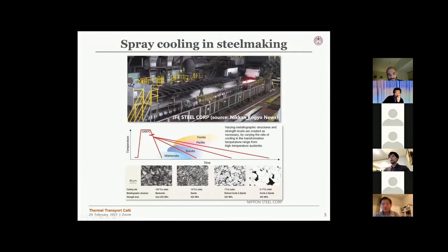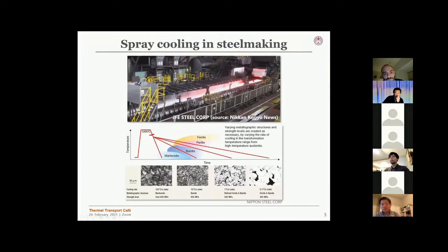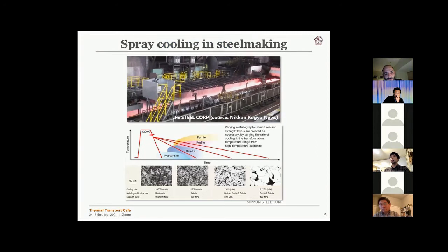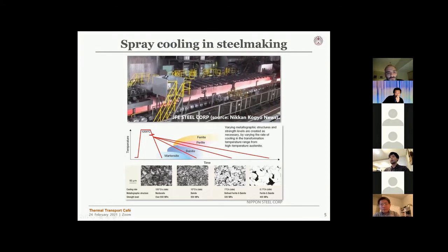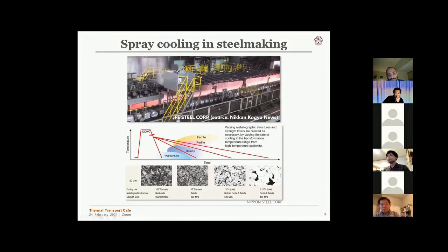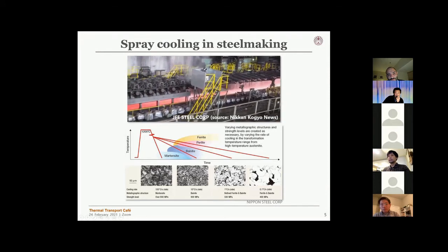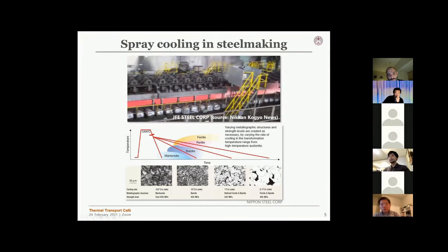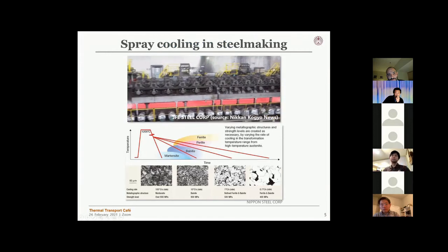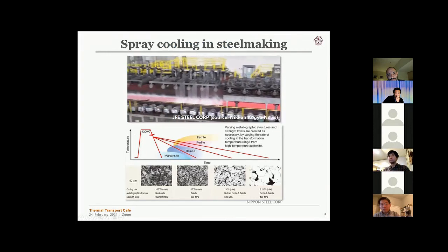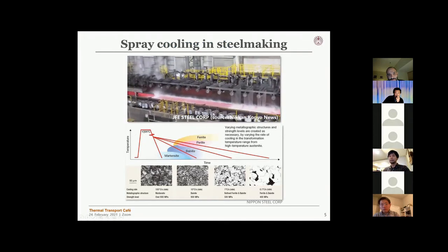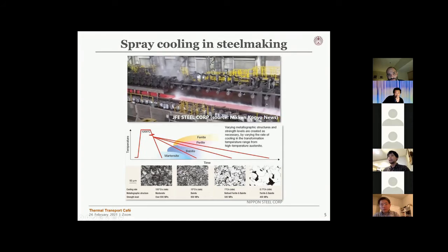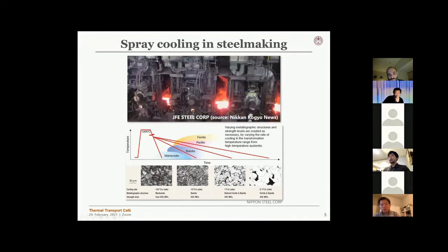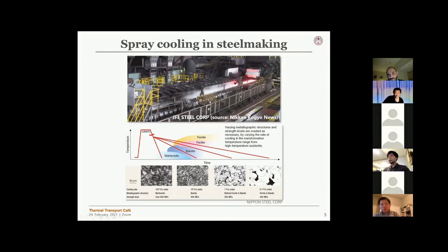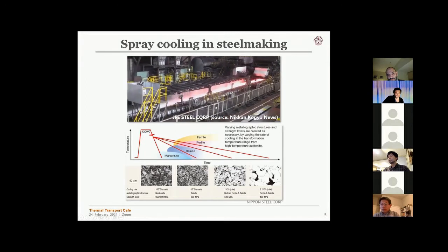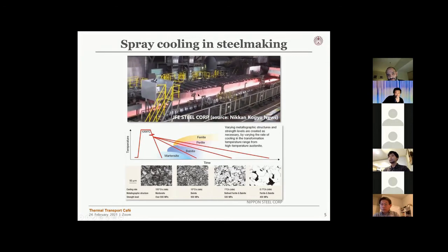This is a video of a hot rolling process at a steel company. You can see that this red steel plate, which means it is very hot, right? Apparently the temperature of this plate is around 1000 degrees Celsius, and it goes through the line, and you see lots of water sprayed onto the surface to cool it down.